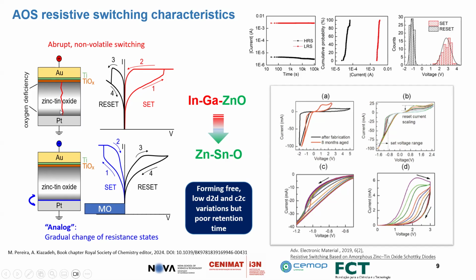So in amorphous oxide semiconductor, for example in the case of zinc tin oxide that we published in 2019, we observed that if we change the polarity of resistive switching, we can change it from one filamentary mode to the area-dependent resistive switching. Here in the area-dependent mode, set happens on the other side of the voltage polarity, and then reset on positive. At the same time, we call it analog resistive switching, gradual change of resistance, and this is abrupt, which is non-volatile resistive switching.